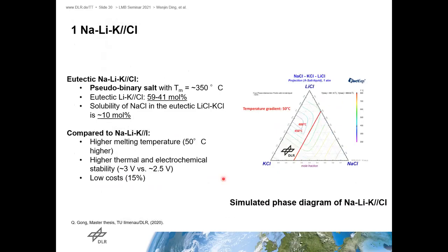Then we also studied the chloride salt systems. Compared to the iodide, it has a little higher melting temperature, about 50 degrees higher, and the properties are similar to the iodide. Sodium chloride is dissolved in the eutectic lithium and potassium chloride salt mixture, and its solubility is about 10 mol% from the simulation. But compared to the iodide salt, it has higher thermal and electrochemical stability and lower cost.